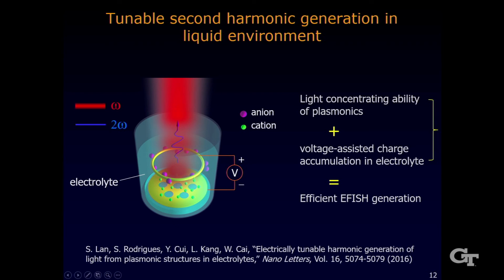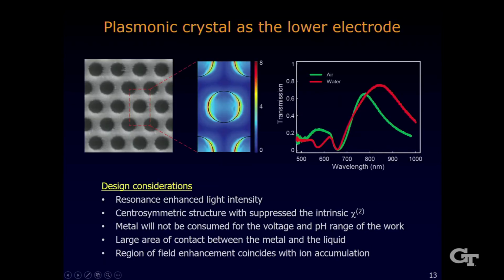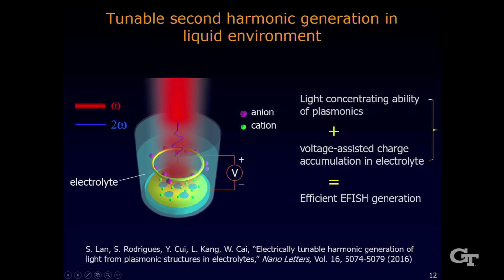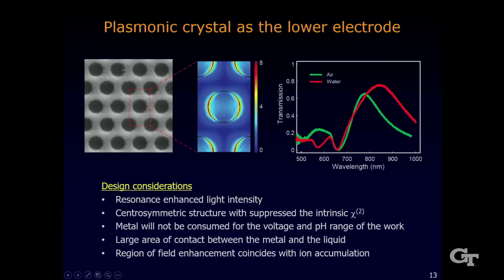okay? So if you place the entire structure in the electrolyte and then apply a voltage, then the free ions in the liquid can flow towards and get accumulated on the metallic structure. This gives rise to very efficient electrical tuning of the nano-optical output, which is potentially useful for biochemical sensing and the signal generation or signal detection in liquid environment. So the lower electrode in our configuration is this hexagonal array of plasmonic holes.